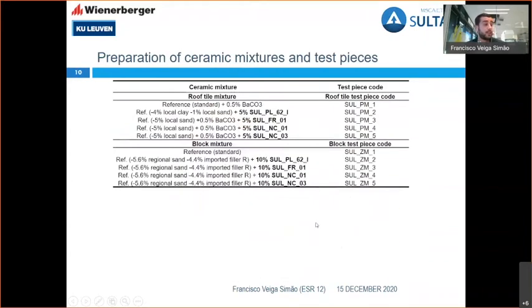So for the preparation of the ceramic mixtures, as mentioned, I started with 5% in roof tiles and also 10% in blocks. With that, I look at the grain size distribution and especially the sieve residue, the over 50 micron fraction, and also try to balance the mixtures. And of course, if you take clay, you should replace it with a clay-like material. In this case, the Plombières tailing material is the best fit. That's why you see here that we took 4% of the local clay and only 1% of sand, while with the others we took 5% from the sand.